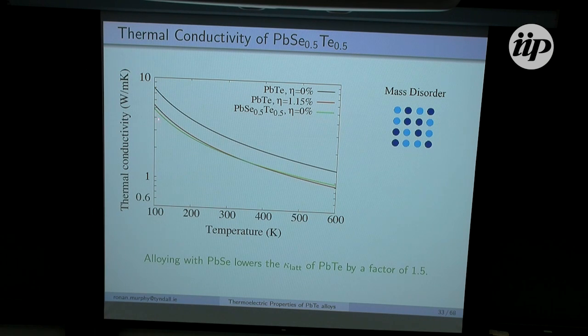Calculating the thermal conductivity of this alloy, we get this green curve here, where again we get a reduction by about a factor of 1.5 due to the effects of mass disorder. Now in this case, coincidentally, it happens to line up very well with the strained lead telluride case, but there's no reason it should. But now I want to talk a bit about how we take this alloy and, as we did for lead telluride, apply tensile 001 strain again.